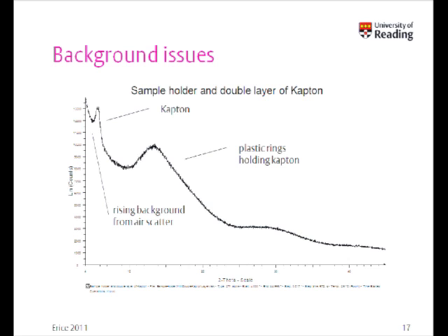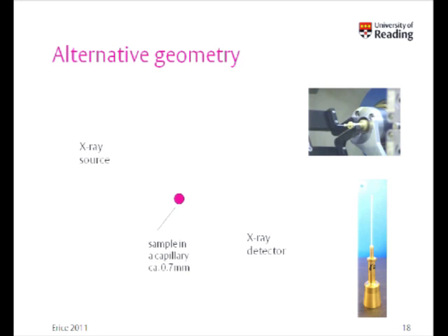We can get round that just by simply narrowing the beam at the monochromator exit slit, and then this part will disappear completely. And that's important because if we're looking for weak reflections, particularly in indexing, we don't want to be fighting effects such as this that will help mask the coherent diffraction. Bragg scattering, I should say.